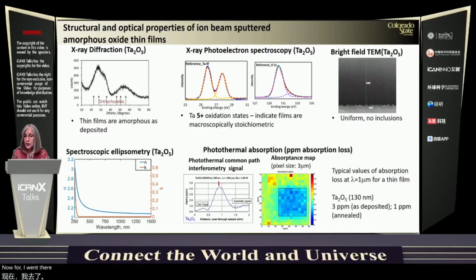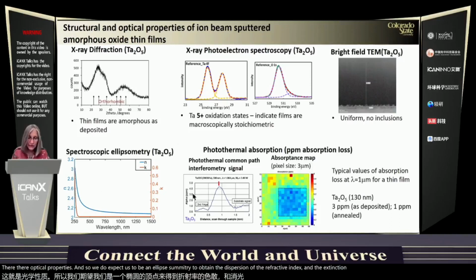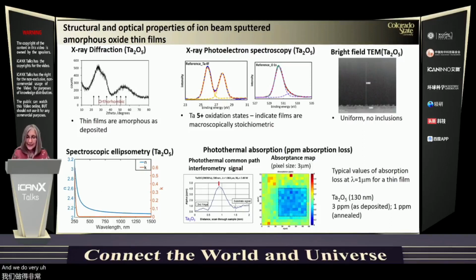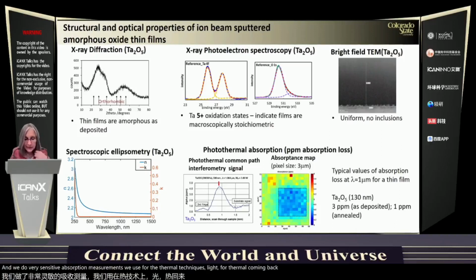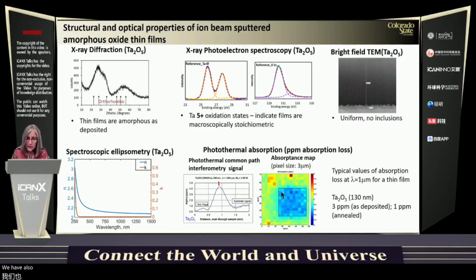Now, for our purpose, we need to characterize very well their optical properties. And so we do spectroscopic ellipsometry to obtain the dispersion of the refractive index and the extinction coefficient. And we do very sensitive absorption measurements. We use photothermal techniques like photothermal common path interferometry, which was developed by our collaborators at Stanford and has a sensitivity below 1 part per million. We have also, in collaboration with the University of Buenos Aires, developed a photothermal technique that can map absorbance also with a high sensitivity in the parts per million and a pixel scale of about 3 microns.